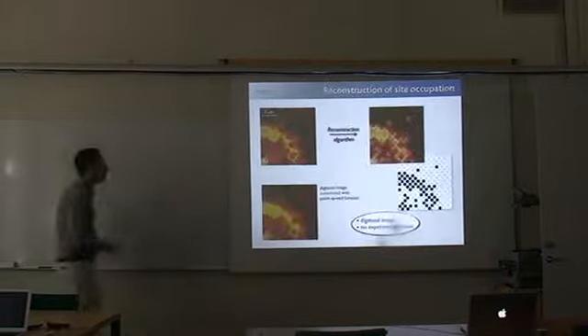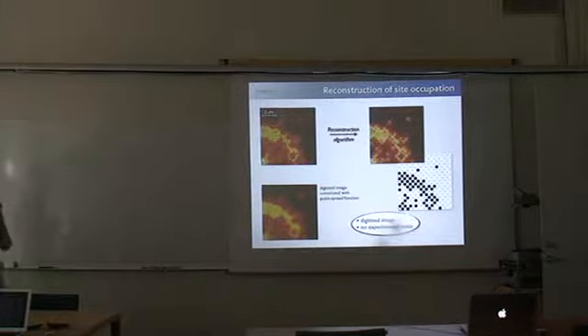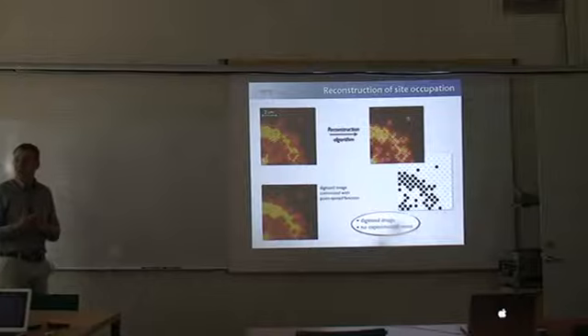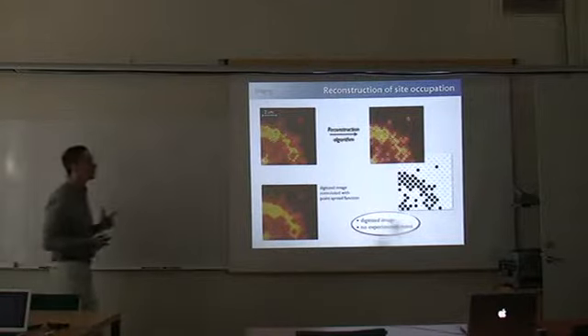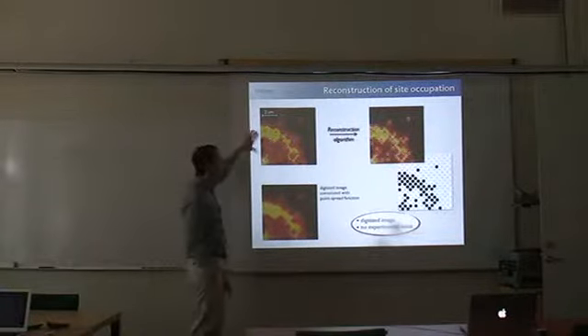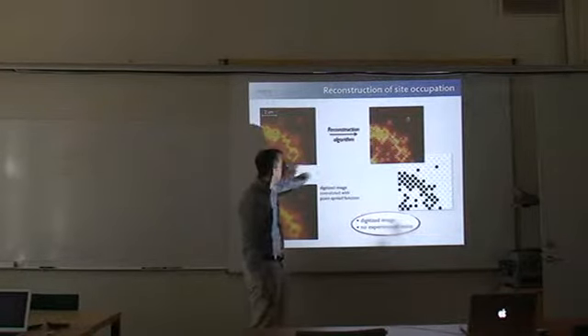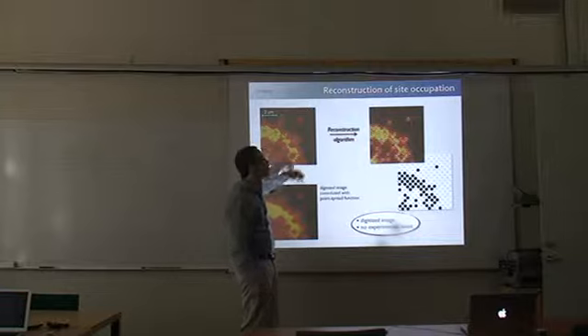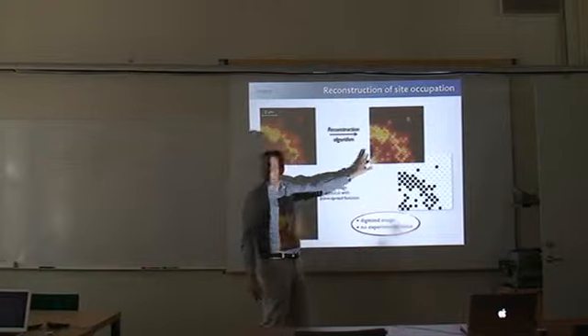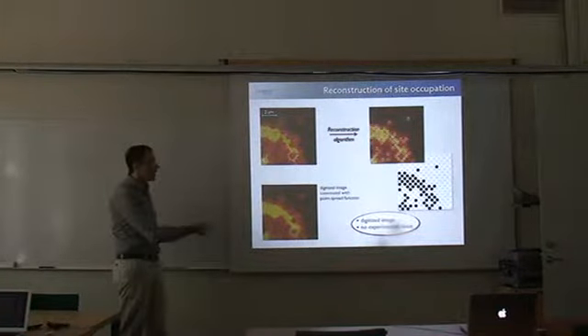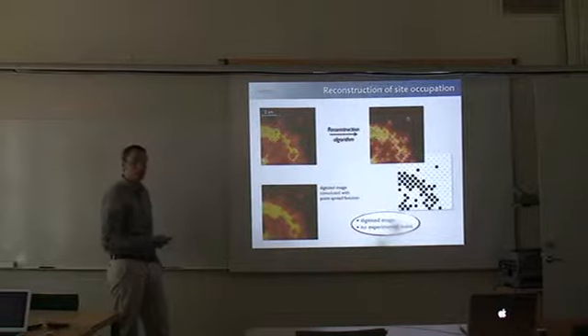Okay? This projection method, and this knowledge that the particles are sitting on a lattice, helps us to basically now convert this into digital images. Which is fantastic from an experimental point of view, because I can take an image like this, the real fluorescence image, and run a reconstruction algorithm which puts these two facts, the lattice and the point spread function, into the system, and basically finds where there were single atoms in the system, or these modulo 2 detected atoms. From that, we get a digital reconstruction of the atom distribution in the lattice.